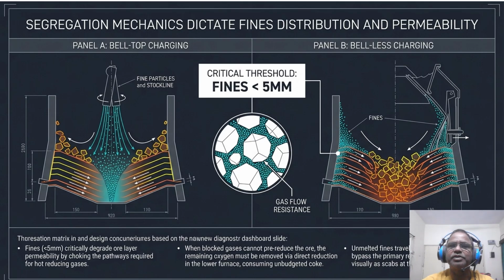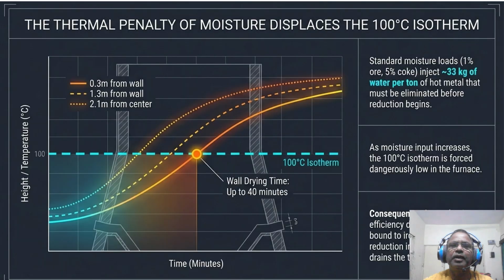Let's look at the numbers. A standard moisture load, just 1% in ore and 5% in coke, injects roughly 33 kg of water per ton of hot metal. This graph plots height and temperature against time. Notice the 100-degree isotherm indicated by the dashed blue line. In a wet furnace, this isotherm is forced dangerously low. For material 0.3 meter from the wall, the solid orange line drying time can skyrocket to 40 minutes.